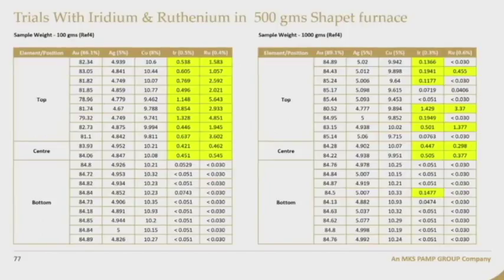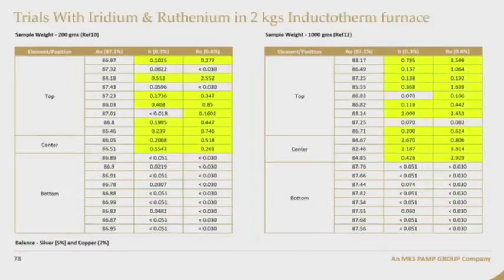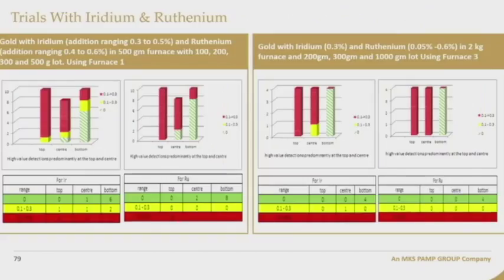The second experiment was adding iridium and ruthenium in the range of 0.3 to 0.4%. With the same exercise of testing XRF at the top, center, and bottom of the sample, we found more concentration at the center and at the top, with even 100 grams or 1 kg of metal. The same thing with melting in a 2 kg furnace, at 200 grams and 1 kg, the emphasis was more at the center and the top. You can see very evidently from this chart that at the top and the center portion, there's more detection of both iridium and ruthenium in almost all the cases.